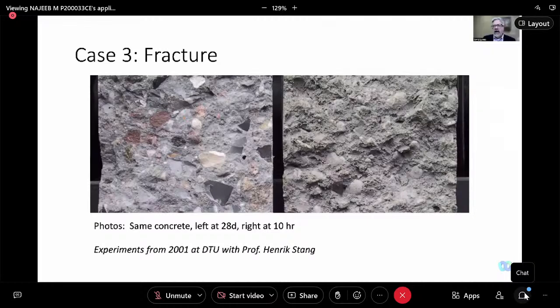There was quite a surge of interest, there still is some research on fracture, of course, but in the 80s and 90s, there was quite a bit of work on fracture because we were looking at this non-linearity, this quasi-brittle behavior that we see in concrete materials. The ones I chose here to illustrate the problem are interesting to me because this is the same material. The test on the right side is at 10 hours old. The test on the left side is at 28 days old. And of course, we all know the strength is very different, but look how the fracture pattern changes. The fracture is very different, explaining in part why the strengths are so very different.